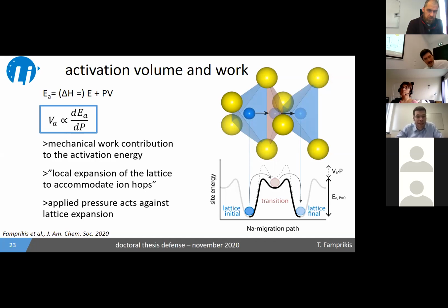Okay, I think along that line, if it really is the anharmonicity of that mode, it's most likely only related to the transition state, but I'm pretty sure we're also, for some reason, changing the initial state. And to distinguish those experimentally, this is really challenging. I think in many structures, you can distinguish between at least metastable states and ground states by temperature-dependent diffraction. Here, you pretty much only have one stable sodium site, so looking at site occupancy evolution is not going to do much here.